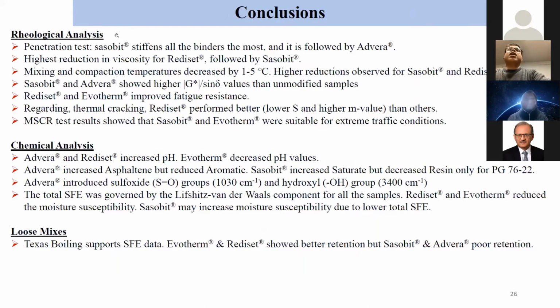Yeah, so we found that the viscosity reduction was most for Rediset, followed by Sasobit. And temperature did not go down by more than 5 degrees Celsius. Higher reduction was for Sasobit and Rediset. And in terms of thermal cracking, Rediset performed better.